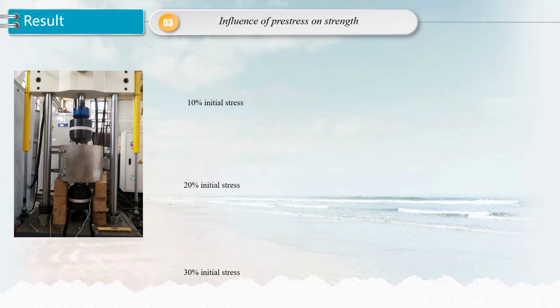The above tests were performed keeping specimens unstressed while heated. However, it is noteworthy that when the fire accident happened on board, high tensile stress exists in steel wires due to self-weight and traffic. To simulate the actual fire scenario, load was applied to some specimens in this study. A specialized test setup was designed to make steel wire heated while subjected to certain tensions, as shown in the left picture.